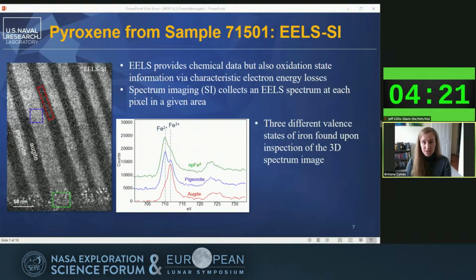To make sure, we then turned to electron energy loss spectroscopy, or EELS, and we discovered it was probably not more iron, but different iron. EELS tells us not just chemical information, but can tell us about the oxidation state of the elements. And in the STEM, we can acquire what are known as spectrum images, where an entire EELS spectrum is acquired at each pixel in a given area, and this generates a three-dimensional data set.